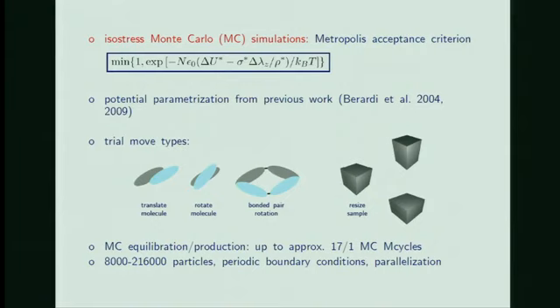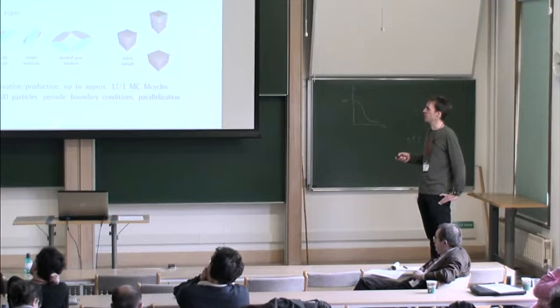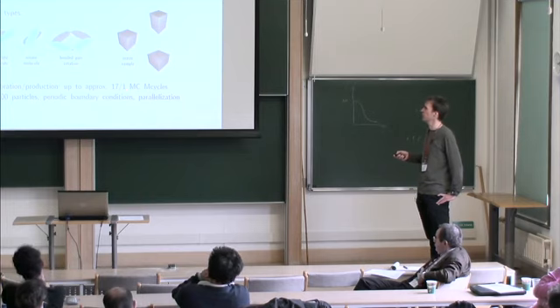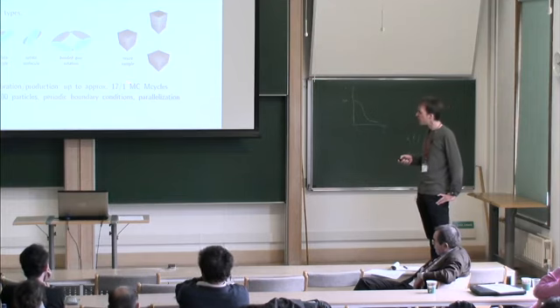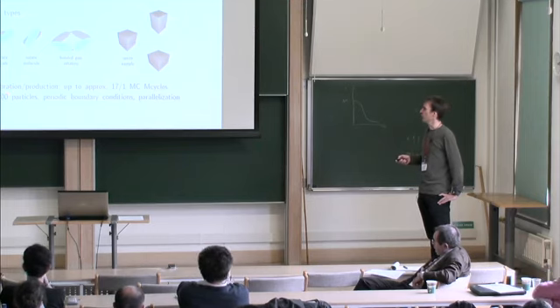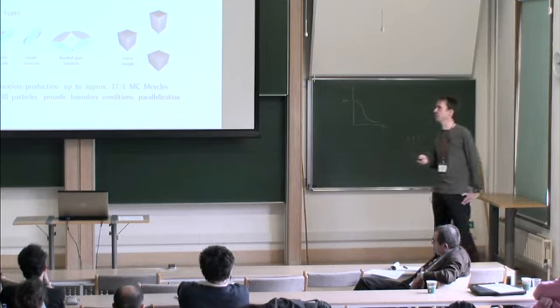Then we perform many Monte Carlo cycles for equilibration and production. Typically it was 17 or up to 20 million cycles for equilibration, and 1 million typically for production. We consider samples of from 8,000 to over 200,000 particles. We impose periodic boundary conditions, and for the larger ones some parallelizing techniques are also needed to obtain results.